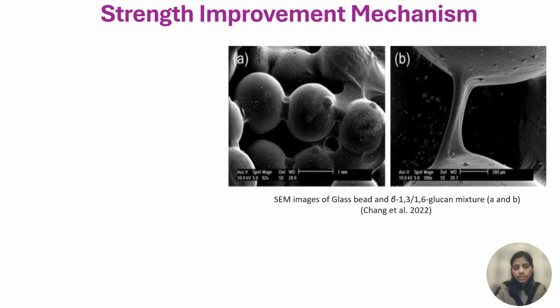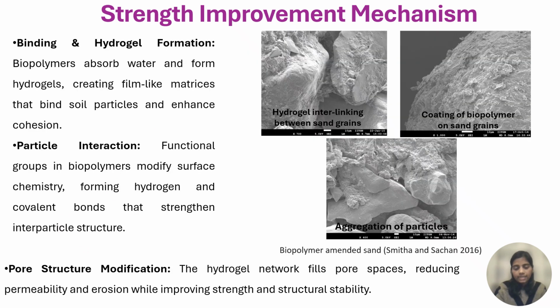Now, there are three main mechanisms behind the strengthening. First, the binding and hydrogel formation. Hydrogels wrap around the soil grains and form thin films that hold them together. These films can increase the cohesion and give the soil a more rigid structure. As water content changes, the hydrogel can swell or shrink, helping the soil stay flexible instead of cracking.